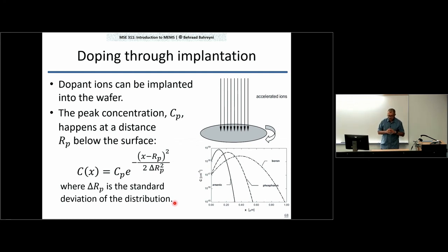And now, this is going to be the equation. So it's like a Gaussian, right? RP is the distance of the peak of concentration from the surface, and delta RP is how wide that peak of distribution is. And Cp is the concentration that comes from the energy that you use, the dosage, and the time. The dosage of the ions that you use to bombard the surface, and how much time you wait. If you want double the concentration, wait twice as long.